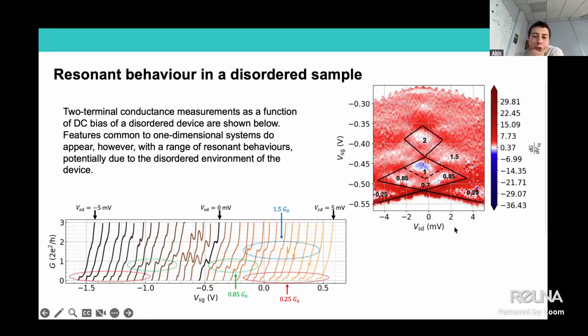And here there is the source drain bias. Usually in a plot like this, you don't see these negative gradients. So you don't see those peaks and kind of dips, etc. And that is thought to be due to this disorder in the system. And most likely it is from that disorder in the system.